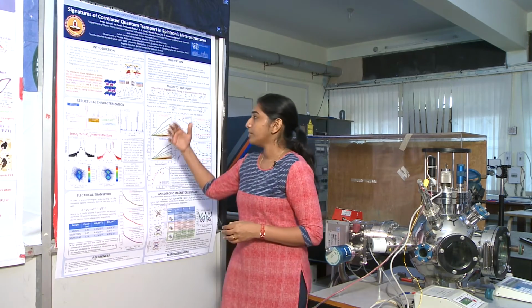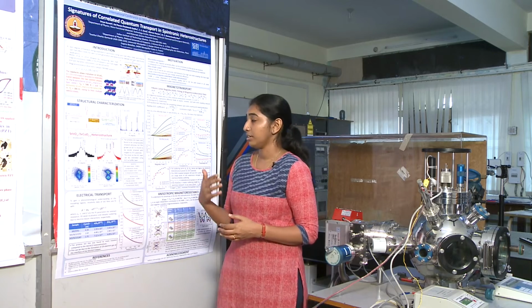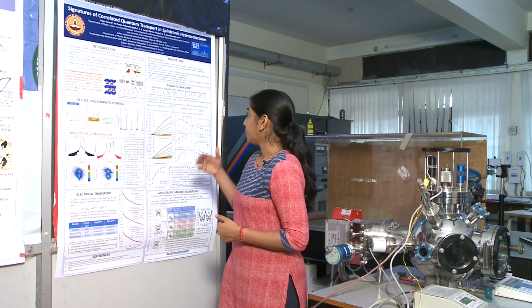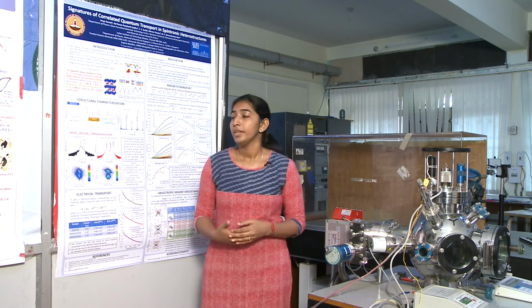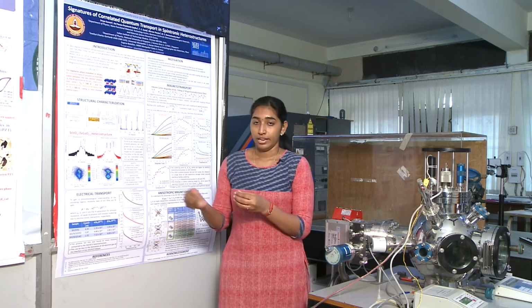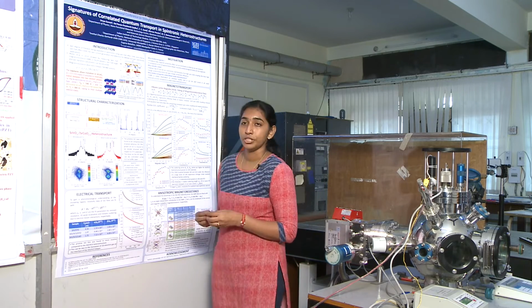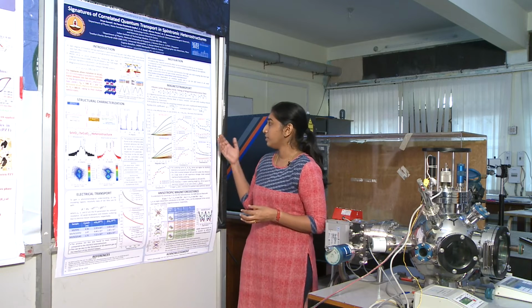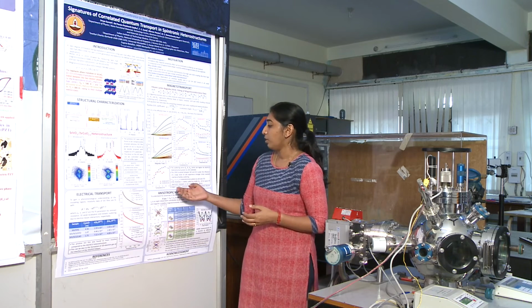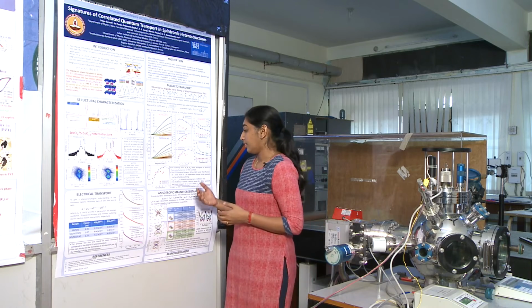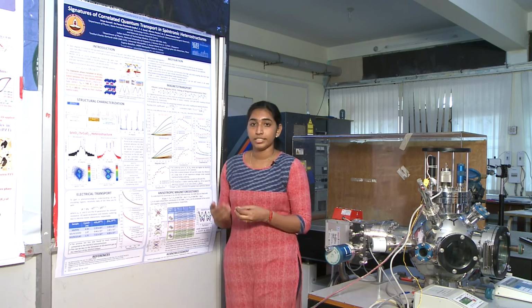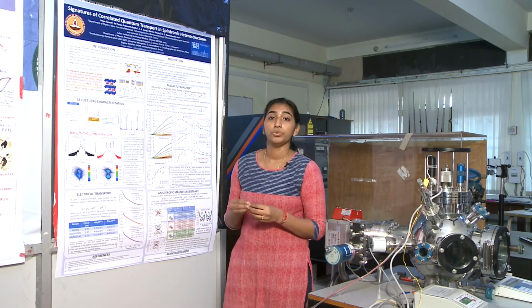and followed by that we have done the structural characterization of this bilayer system using the in-plane XRD, and using the electrical and magnetotransport studies we have done using the physical property measurement system available in our lab. We could conclude that there is an interface charge transfer between iridium and cobalt ions, thus resulting in a two-dimensional electron gas formation at the interface. From the results we obtained from these magnetoconductance measurements, we have seen that the inelastic and the spin orbit scattering lengths were coming in the order of nanometer, which was crucial for quantum nano spintronic device applications.